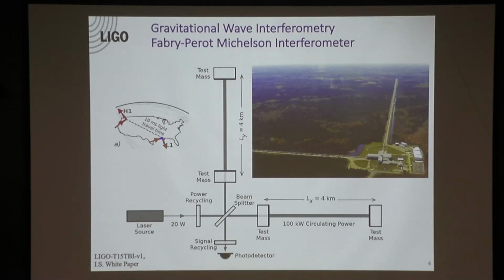And as I will talk about when we get to my own work, one of the things that people would like is silicon, which is a very nice insulator, not great at 1064, we'll come back to that problem, but it is an insulator, and the index of refraction is quite high, more like 3. So it would be much better to have the high index layer be 3 instead of 2. It would enable you to use fewer layers, for example. So this is the bottom line of how this system works. As I said, out of the 4 kilometers, the displacement we're trying to measure is 10 to the minus 19 meters.